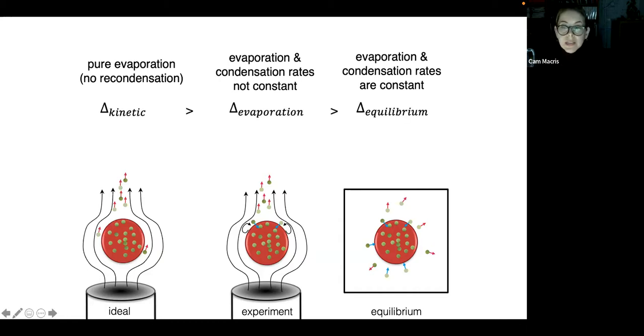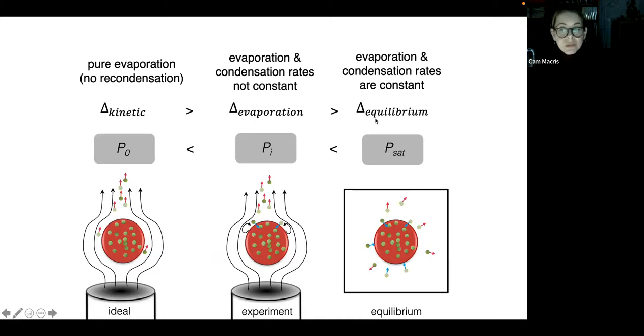So in the free or ideal evaporation scenario, what we have is a purely kinetic isotope fractionation, which is going to be larger than the fractionation due to partial evaporation, as we see in our experiments, which in turn is going to be larger than the fractionation that we would expect at equilibrium conditions. These different degrees of fractionation and rates of evaporation versus condensation are going to be dependent, at least in part, on the partial pressure of the evaporated particles at the surface of the melt. In our purely kinetic case, the partial pressure is going to be 0, which is lower than the partial pressure in our experiments, which is lower than the partial pressure at equilibrium, which would be saturation.